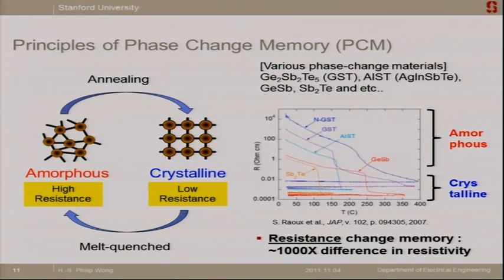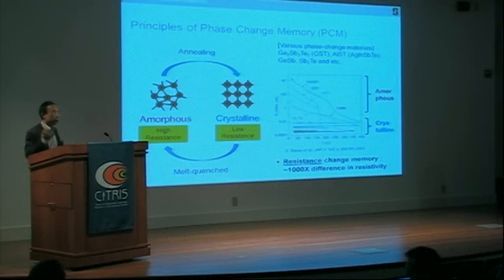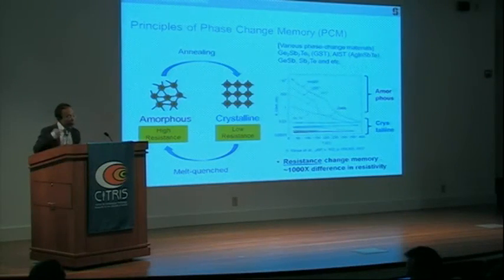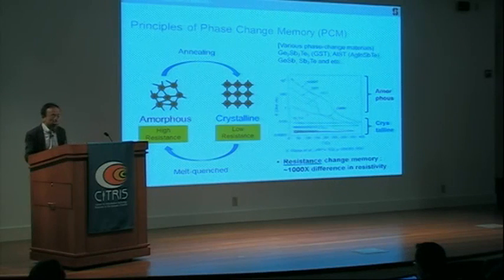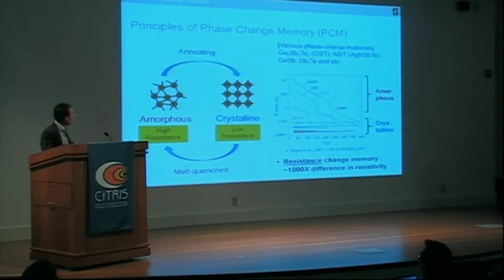All right, phase change memory. The physical principle is very simple. You have a material, various kinds of materials, and we heard about some superlattice phase change material yesterday, which is quite exciting. The basic principle is that the material can transition between amorphous and crystalline states by heating it up, passing currents through the material, and through Joule heating, you heat up the material. If you heat it up beyond the melting temperature, melt it, and then quickly quench it, it becomes amorphous. And if you want to put it from the amorphous state to the crystalline state, you heat it up at an intermediate temperature beyond the glass transition temperature, so it will begin to nucleate around the nucleation sites and recrystallize in a polycrystalline state.